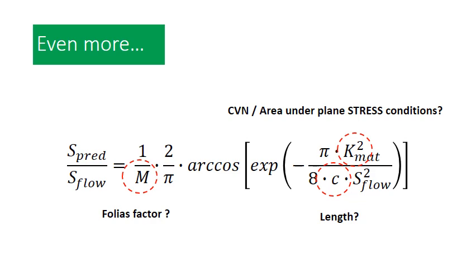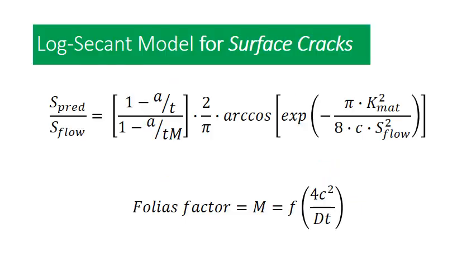Now, strictly speaking, that's not technically right. Toughness correlations should be done under plane strain conditions, but in this case it's okay because we're dealing with relatively thin wall pipe. If you think about it, the crack tip that's looking to extend is going to be able to strain and pinch in radially, absorb energy, and end up with a higher apparent toughness. So this is all good. I'm happy with this model. So I give it the green light from top to bottom.